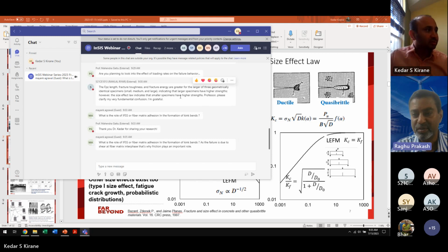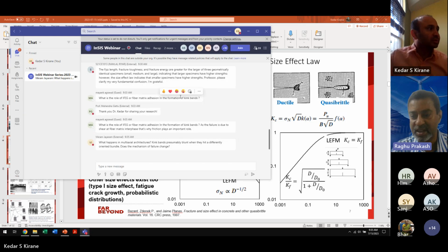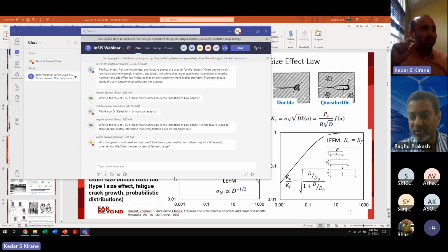There's one question from Mayank Agarwal. I think he has typed twice. He says, what is the role of IFSS or fiber matrix adhesion in the formation of kink bands? And as the failure is due to shear at the fiber matrix interface, that's why friction plays an important role. Yes, absolutely correct. That's a great question, and in fact that is one of the crucial quantities. If the fiber matrix adhesion can be improved or made stronger, the resistance to failure by kink band will increase.